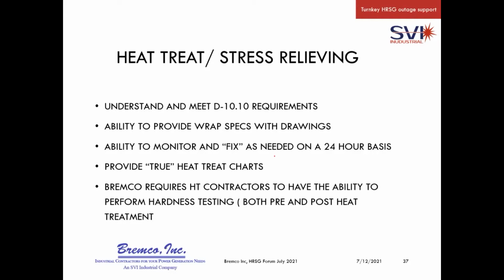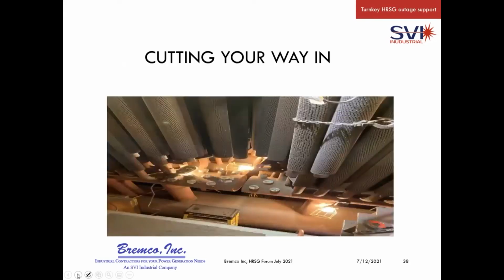With 91, again, hardness testing is a very important requirement. And what we do is we do both a pre and post heat treat to make sure that that 91 falls within the applicable hardness grades. We have run into situations where we've had soft 91 and we've had to make some adjustments. We found the hardness testing to be soft based on the initial inspections, and then we had to make some adjustments to the repairs that we did for that.